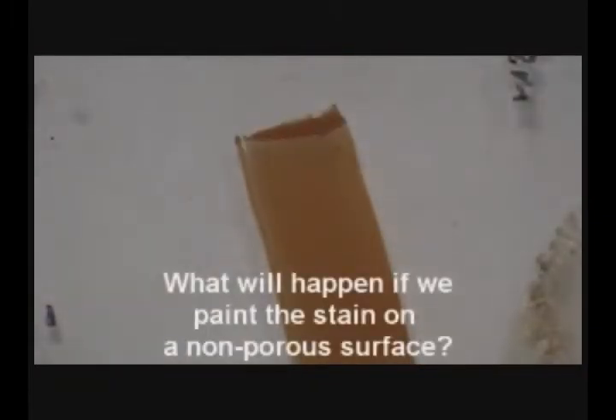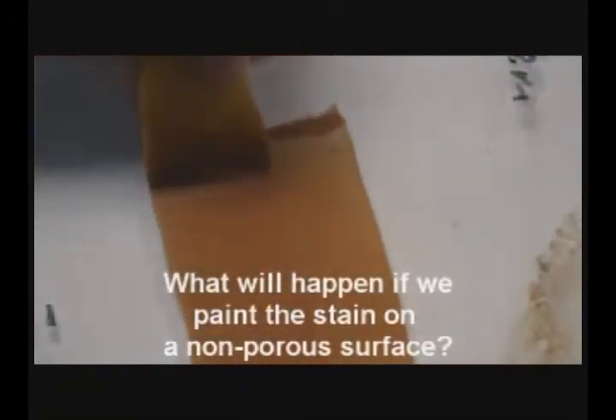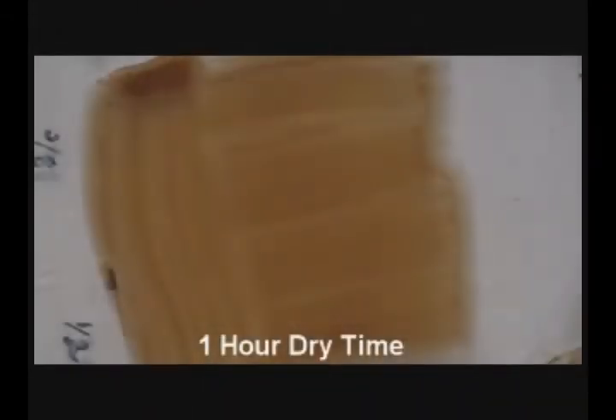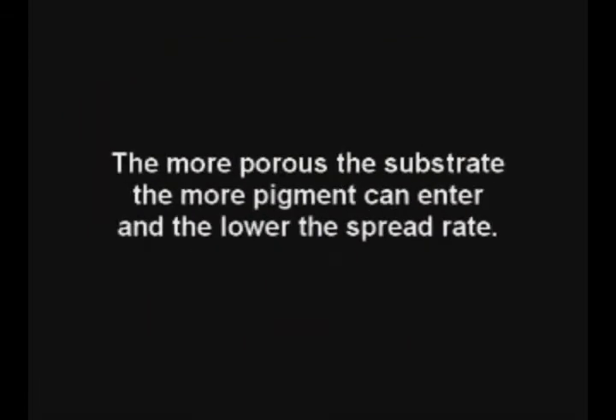Notice how the stain color is being pushed to the side. It cannot penetrate this surface. What will happen if we paint the stain on and wait for it to dry? After a 1-hour dry time, it wipes right off. So with no porosity, we get very little, if any, color, no penetration, and extremely high spread rates. The more porous the substrate, the more pigment can enter and the lower the spread rate.